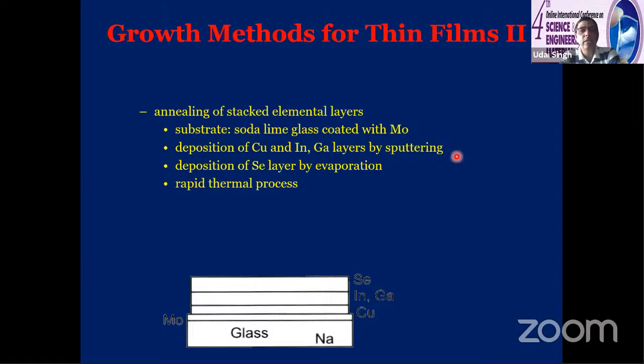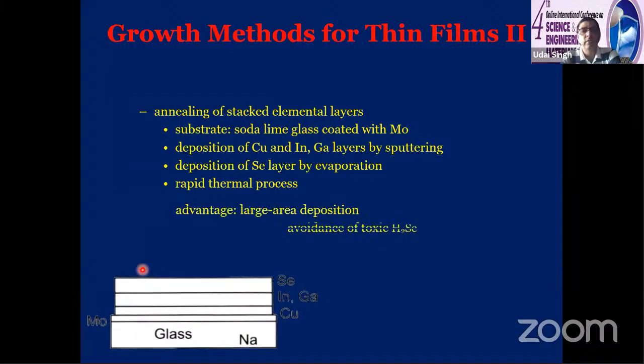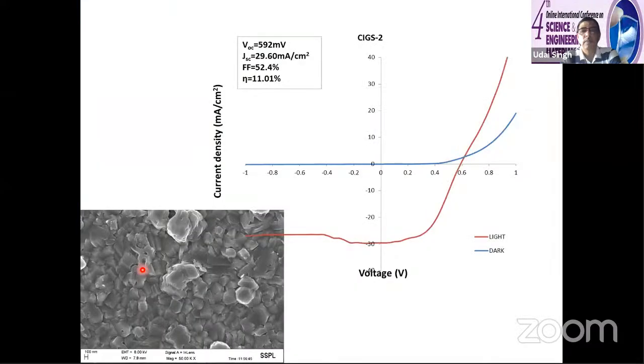So in that case, people have tried to deposit one selenium layer on top of that and then anneal. So it's not very toxic, and then they try to achieve this. So in our lab, with this co-evaporation, we have got the highest efficiency of around 11% on a small area, 0.5 centimeters square.